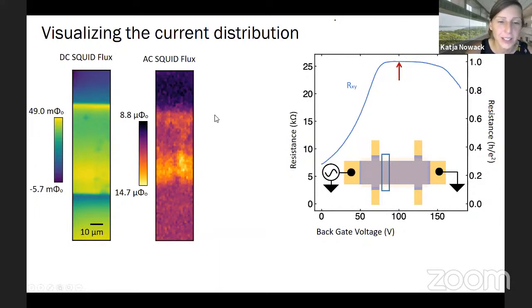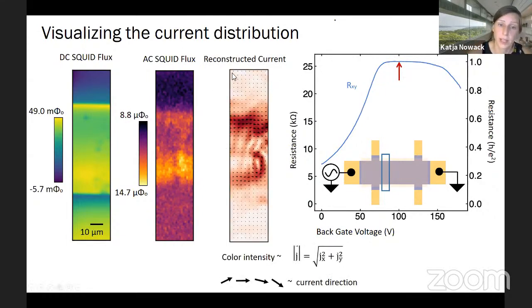I can already tell you that the flux signal looks a lot like a current that is flowing in the bulk of the sample. And I just remind you, we are at about 100 volts where we actually measure quantized transport coefficients. We can do this current reconstruction from this image, and this is the image that we get, where the color intensity, the intensity of the red, gives you the total magnitude of the current, and the little arrows indicate the directions of the current. So we see there are little whirlpools of current, and current flowing predominantly through the bulk.